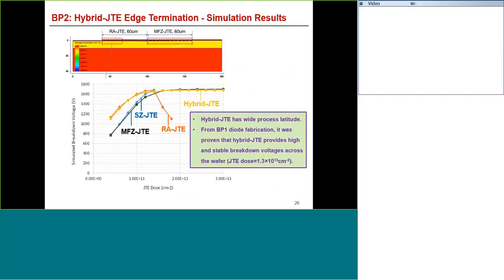So on the lower part of the graph, there are lines indicating performance of various types of terminations. The single zone JTE is a very old one. It's shown by the blue line, and you can see that it's very sharply peaked, meaning that you have to have a very precise JTE dose to make this work. If you deviate from that zone, then the performance degrades rapidly.